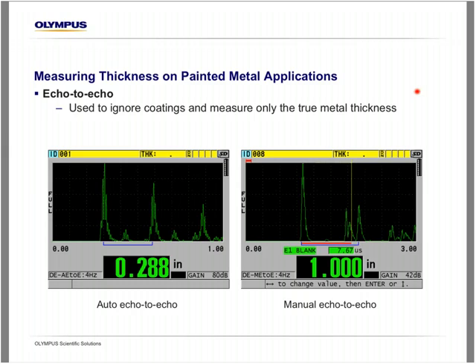So there's no gates to set, so it's much easier and faster setup for that user. But there are some limitations, and these include measuring thick samples, since it's harder to get multiple backwall signals from a thick sample. Also measuring thin materials, and if you're measuring something that's painted that has a severely corroded backwall, because again, you're going to struggle to get multiple backwalls.